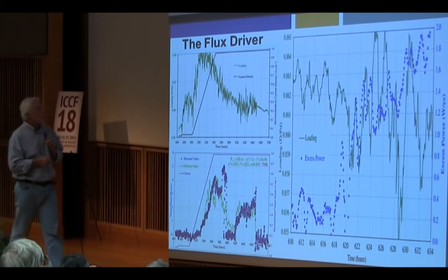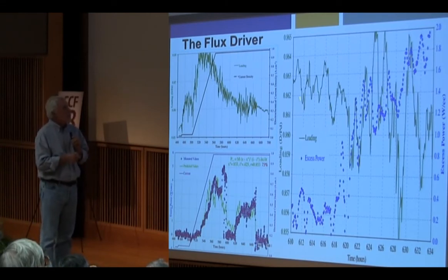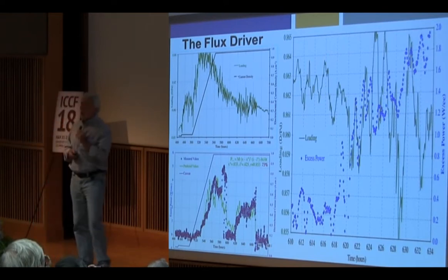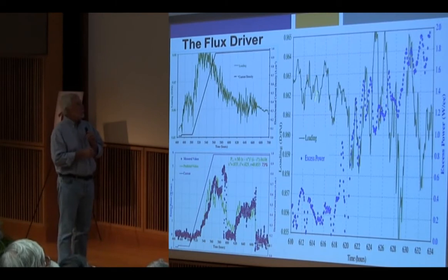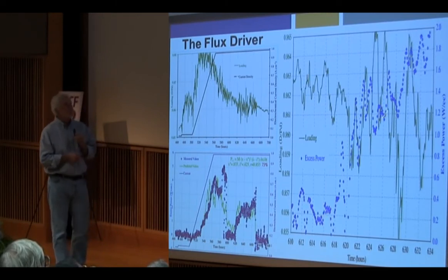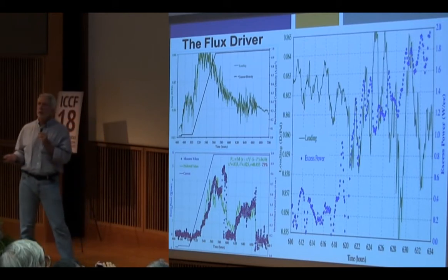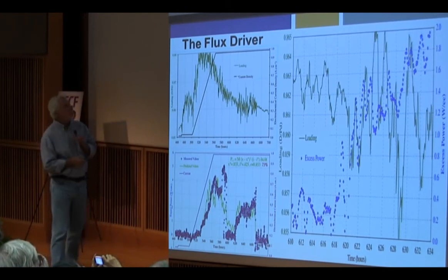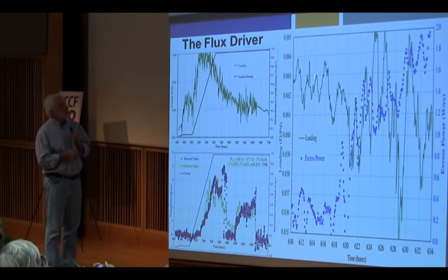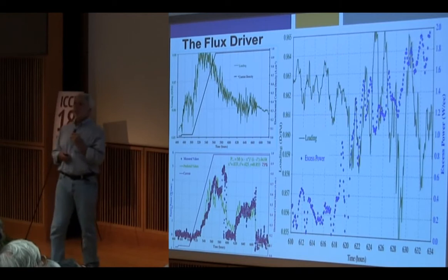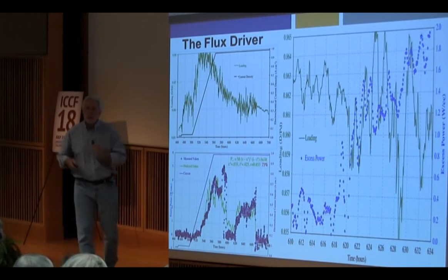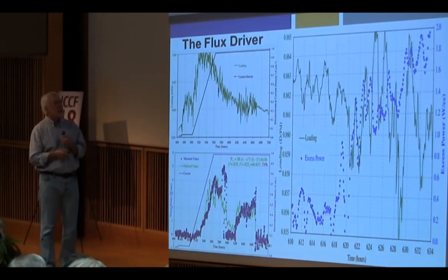And when we looked closely at this, it was a periodic fluctuation of loading. The period about 2 hours. The amplitude of this periodicity changed and affected the excess power. The excess power, this is where the equation that Francesco Celani spoke about yesterday, thank you, Francesco, came from. And the amplitude of this fluctuation, of course, this is loading and unloading, and the electrodes were breathing all by themselves, sort of sucking in deuterium and expelling deuterium with a period of about 2 hours.